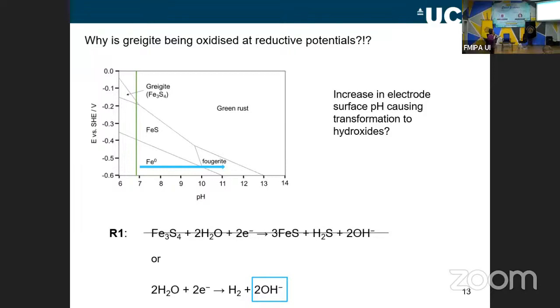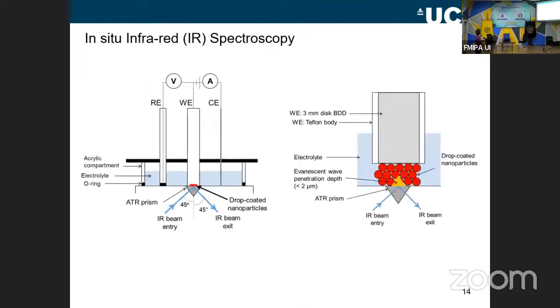So our question was, were we getting an increase in the surface pH, which was causing some kind of transformation to oxides or hydroxides? So the way that we investigated this was another in situ technique. This is in situ infrared spectroscopy. Most of you have probably learned something about infrared spectroscopy, but the type that we used is something called attenuated total reflectance infrared spectroscopy, or ATR-IR.